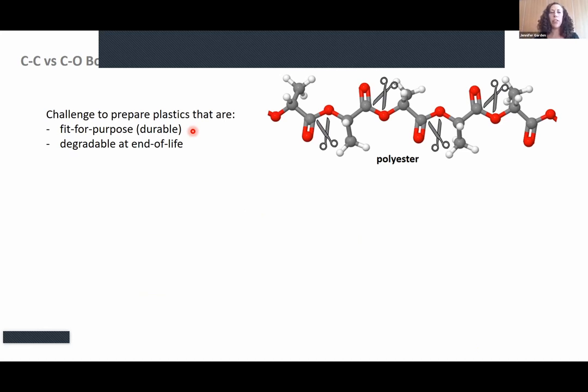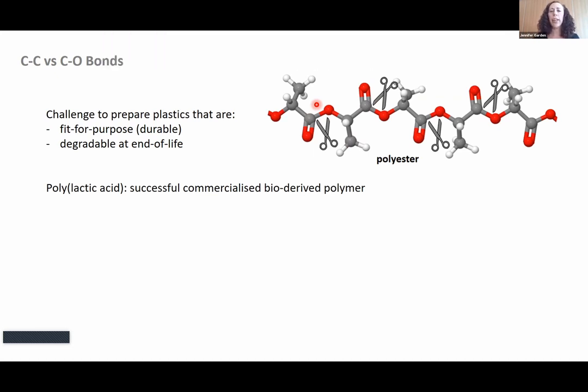So I think an opportunity here comes from looking at incorporating carbon oxygen bonds into the polymer structure. Many conventional plastics have strong carbon-carbon bonds in that polymer structure, like polyethylene and polypropylene. Whereas if we introduce carbon oxygen bonds in the form of polyesters, such as polylactic acid, which is shown in the top right here, then we introduce these breakpoints into the polymer chain. Polylactic acid is arguably one of the most successfully commercialized polymers that's made from biomass. So it can be made from plant materials like sweet corn or sugarcane.